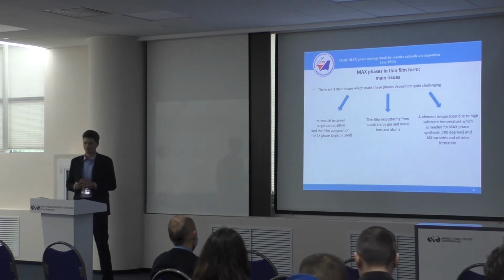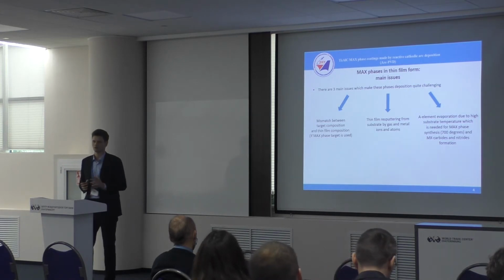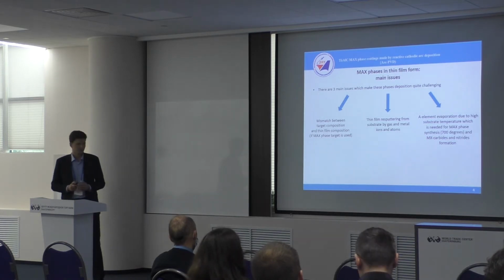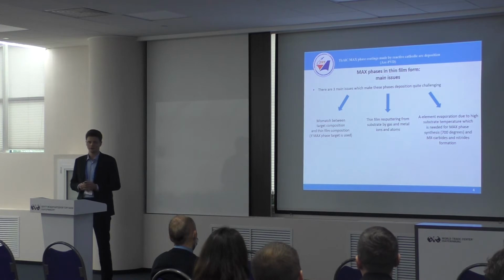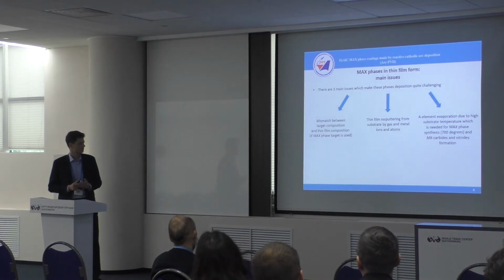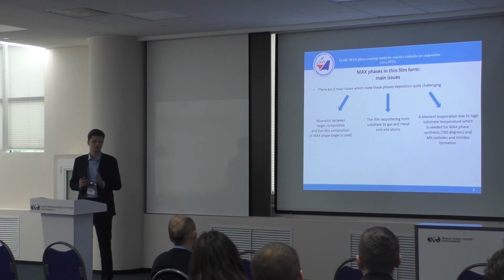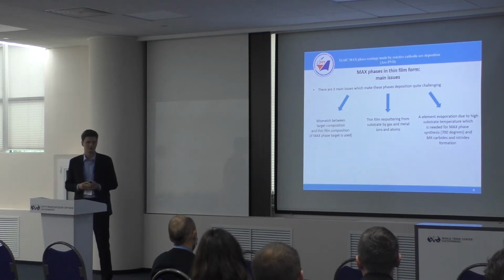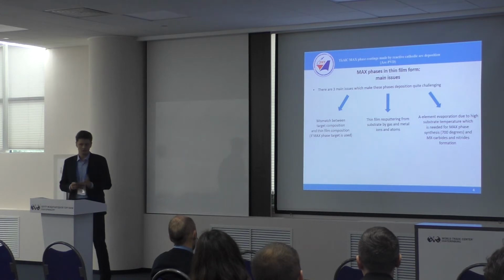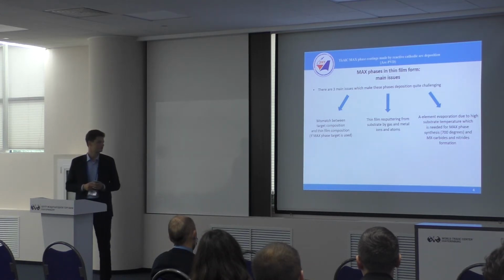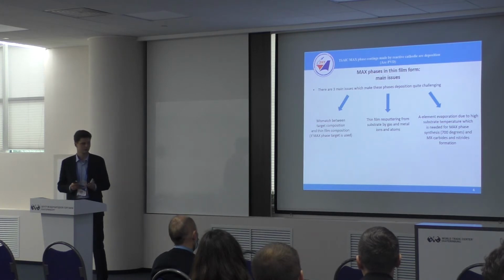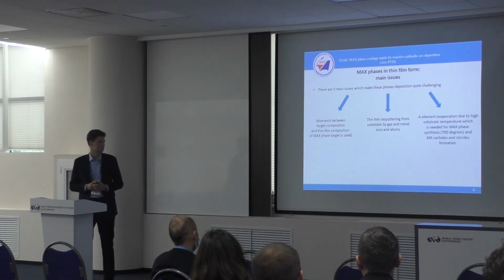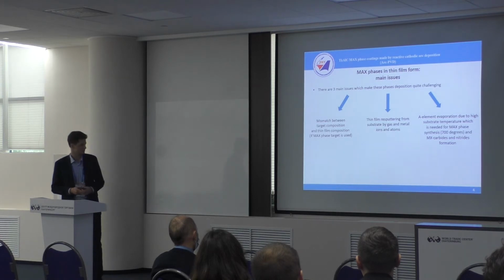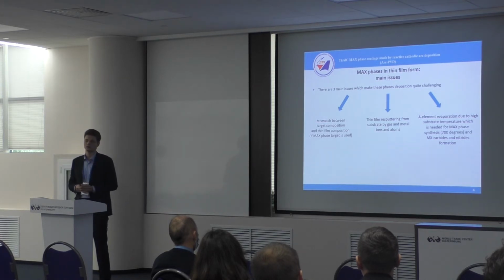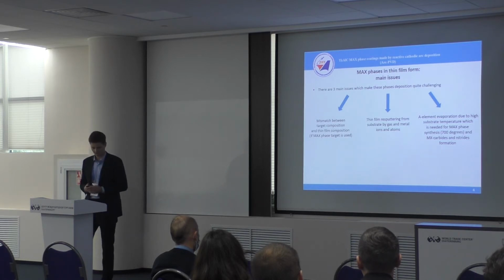It is the mismatch between target composition and thin film composition, if we talk about compound sputtering, MAX phase target sputtering. This is thin film resputtering by heavy ions and atoms, especially if we talk about systems with really different elements, for example tantalum and aluminum carbon. And the third problem is element evaporation due to the high substrate temperature which is needed to provide synthesis of MAX phases. It's typically more than 700 Celsius degrees, which is far above the melting point of most A elements.